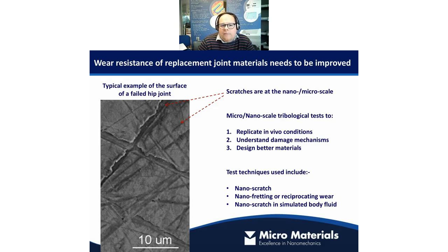And so the fact that we can actually produce in a controlled way damage scars of this kind of scale, and we can combine that technique with measurements of friction on the indenter tip, and we can combine it with the environmental control to simulate the in vivo conditions that the joint lives in, means that we've got a pretty powerful tool in our hands for starting to simulate what may well happen with different materials in the body environment, in that dynamic tribological environment.